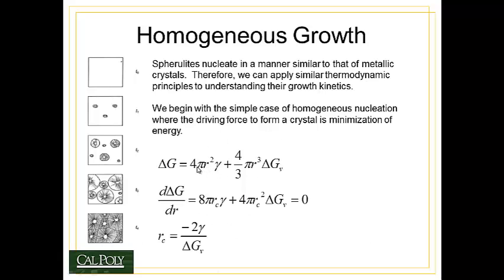The surface area of the spherulite, its energy is equal to 4πr² times the surface energy of the spherulite, plus 4/3πr³, the volume of the spherulite, times the free energy change associated with creating this new crystal.